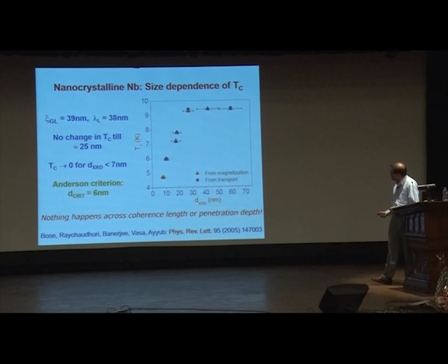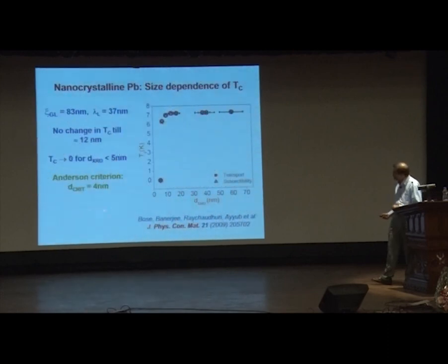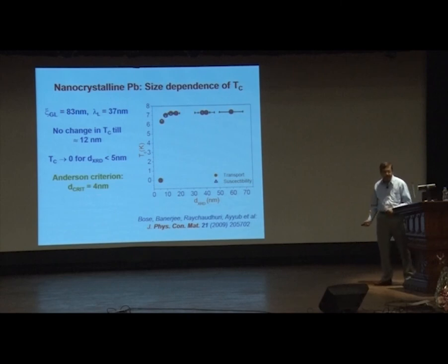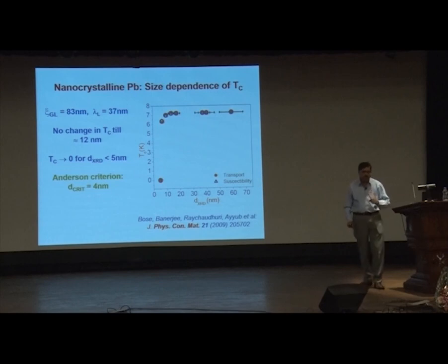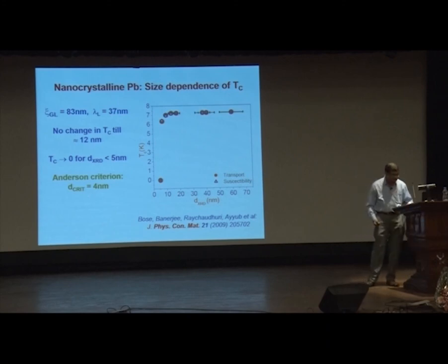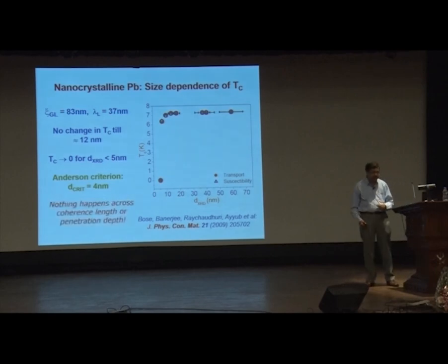For lead, another classical superconductor, the Anderson criterion gives 4 nanometers. It remains superconducting till about that size and drastically falls to zero at 4 nanometers. This back-of-the-envelope calculation suggested by Anderson is extremely robust — for most materials it is valid to almost ±0.5 to 1 K. It is a beautiful application of the quantum size effects theory.